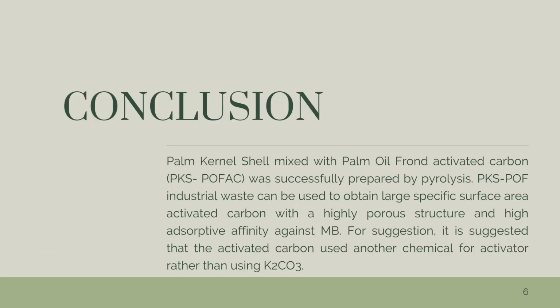To summarize, palm kernel shell mixed with palm oil frond activated carbon was successfully prepared by pyrolysis of the sample for 15 minutes in a customized microwave oven at a fixed temperature of 800 degrees Celsius in the presence of nitrogen gas. The findings indicate that palm kernel shell and palm oil frond industrial waste can be used to obtain large specific surface area activated carbon with a highly porous structure and high adsorptive affinity against methylene blue.